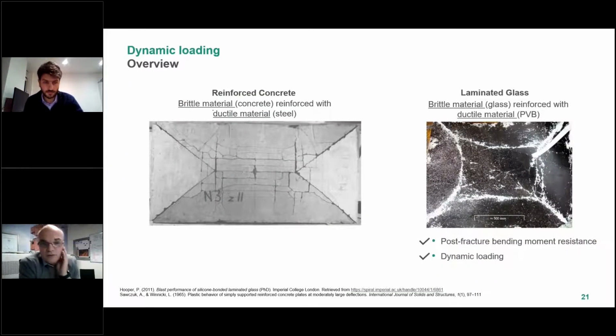Yeah, nice. And you were showing the comparison between the concrete on the left and the glass on the right, and you explained the dynamic loading. But the actual formation of the plastic yield lines, shall we call them that, in the glass, these are to a large extent not a function of the fragment size, right? Or here there's a lot of fragmentation, so the yield lines form. So I wonder, does the fragment size affect the formation of the yield lines?